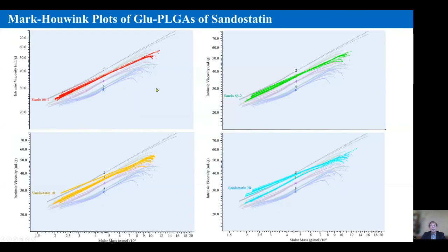This is an example. So the way we did it was using a model of glucose, not Glu-PLGA, model branched molecules based on branching number 2, 3, 4, 5, 6. Now, if you compare the intrinsic viscosity of the sandostatin sample, you can see that at the low molecular weight the branching number is about 2, 2.5, and as molecular weight increases, the branching number increases to 3, up to 4, sometimes more than 4. So with the same sandostatin, if you use a different lot, or the same lot from a different time of the day or different days, they have a slightly different profile.